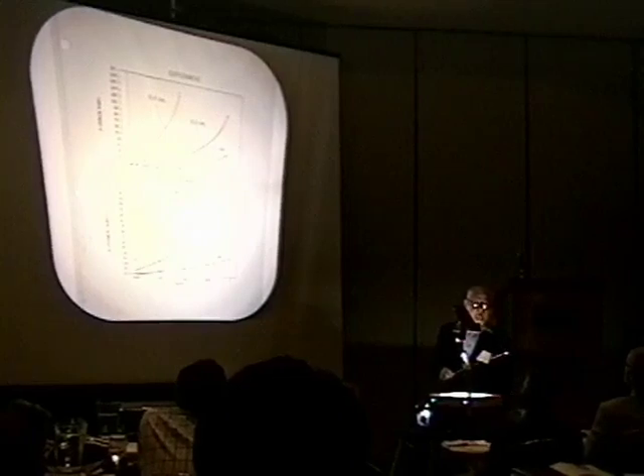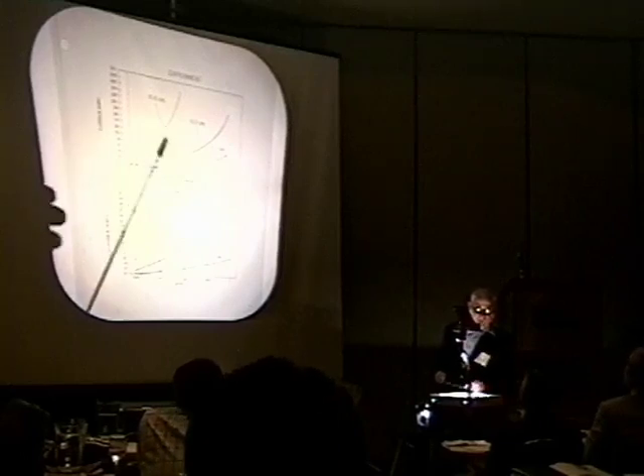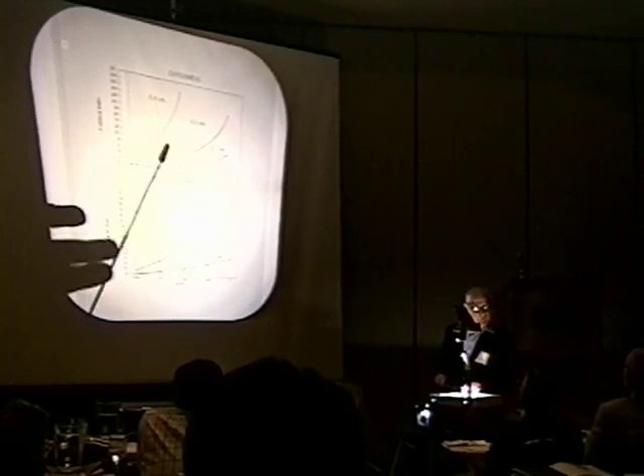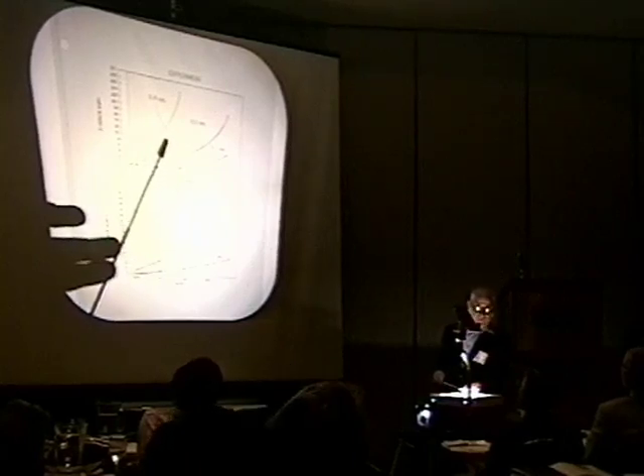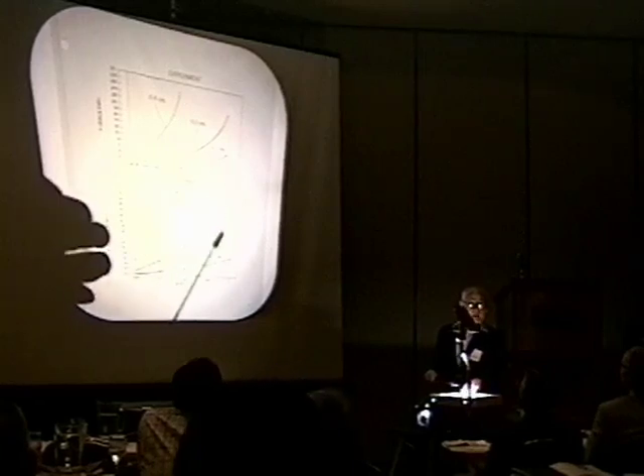The solid lines here represent 15 points, which I call baseline, because they're a consistent pattern. This dotted line is 5 points, which I'm calling non-baseline points, which are the same diameter as this, but simply don't follow the pattern. It's shifted to the right. I think there's good reason for it, but I'm going to ignore these points from now on, and if you get into detail after getting the paper, you'll find that their presence or absence doesn't affect the conclusions. Two very dramatic things.